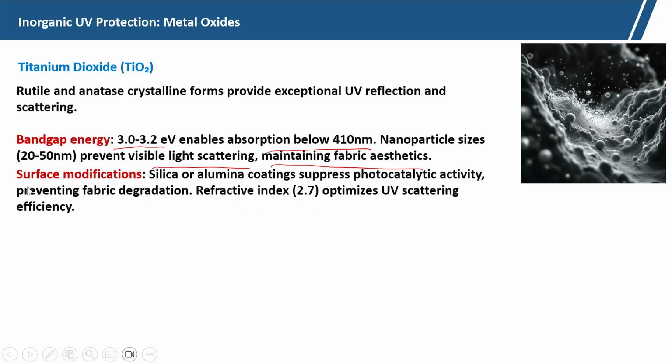And the surface modification capability: the silica and alumina coating suppress the photocatalytic activity, preventing the fabric degradation.